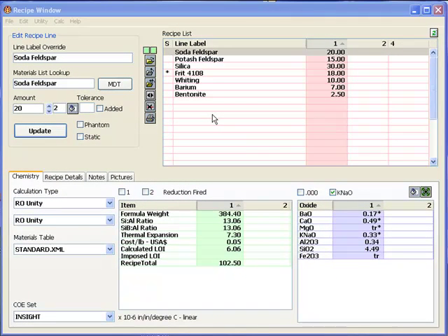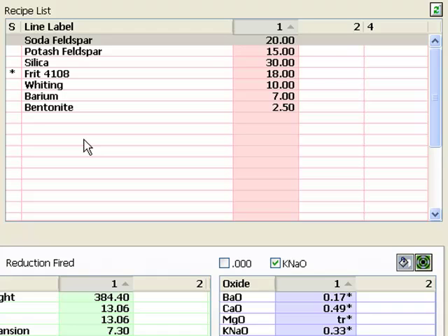Before going any further, I just want to explain a little bit further. A ceramic glaze is not a solution, it's a suspension. In other words, it's a bunch of rock powder stirred up in water, simplistically. And normally that rock powder should not stay in suspension, it should sink to the bottom immediately after you stop stirring. But because glazes contain clay, the clay holds all of the other powders in the mixture in suspension. But in order for that to work, you need at least about 15% kaolin, or 10 to 15% ball clay.